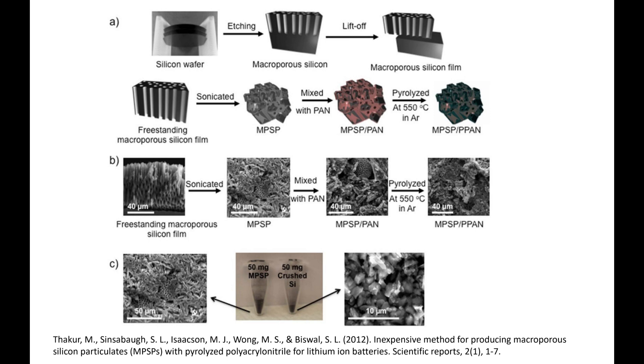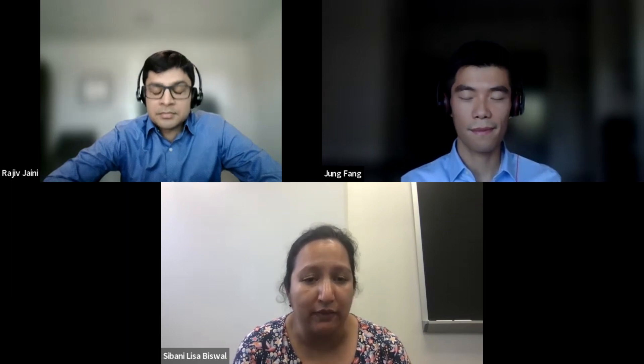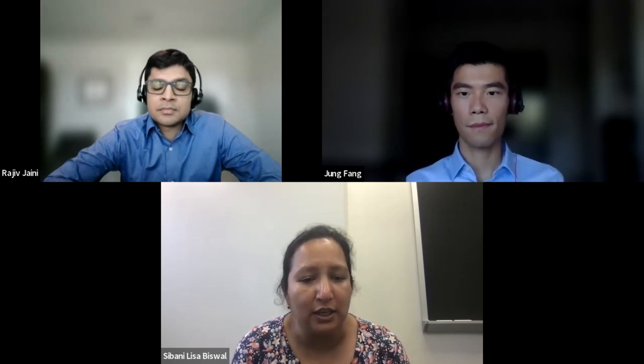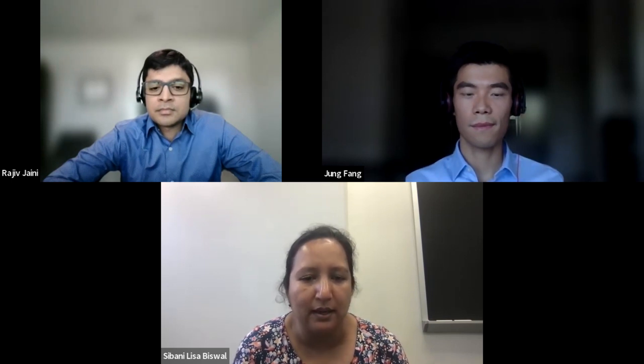Silicon actually has a much higher capacity for lithium than existing carbon-based materials like graphite — almost 10 times as much capacity. But the problem with silicon is that it swells significantly when it lithiates. By increasing the surface area to volume ratio through creating extra void spaces in the silicon, we can accommodate some of the stresses that happen in the material as it swells. With our assembly method, we make a composite — we take the porous silicon and embed it in a conductive polymer, which provides a binder material and helps accommodate stresses as the material tries to swell when it alloys with lithium.